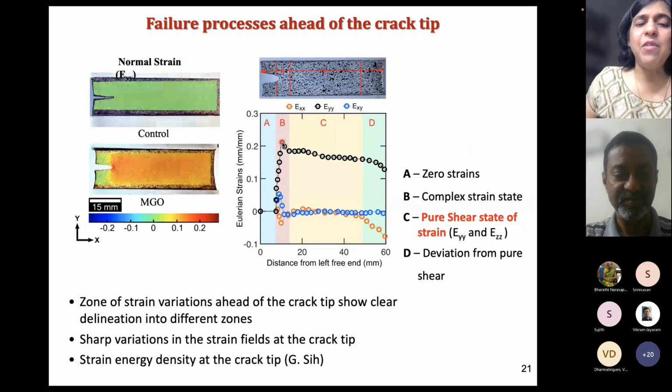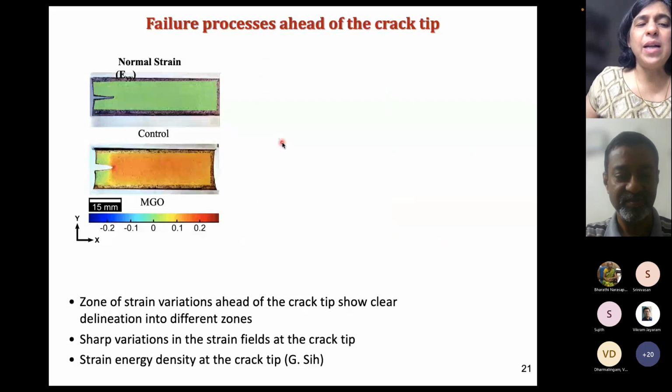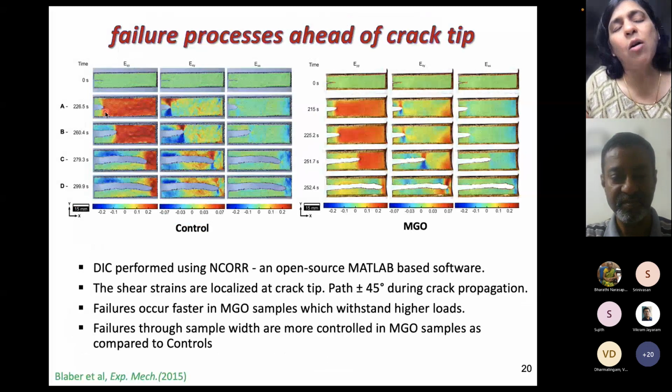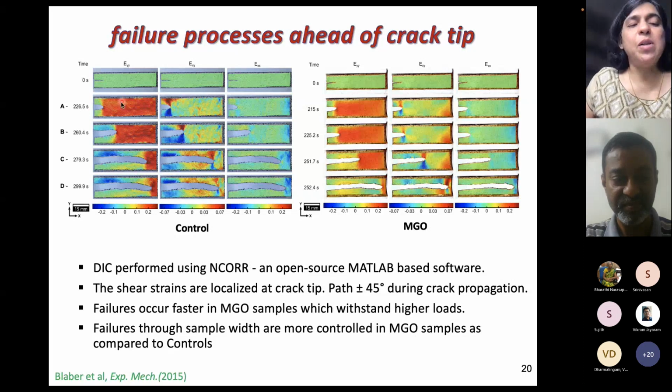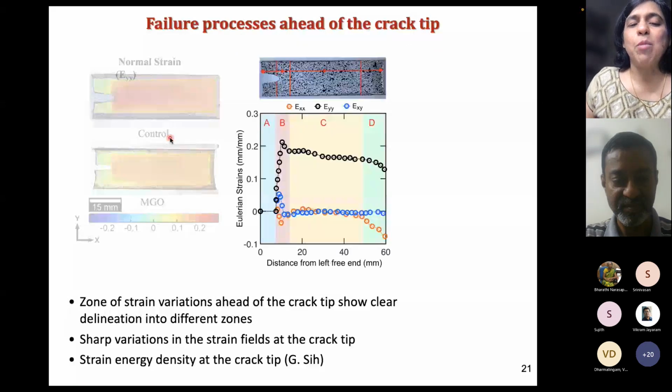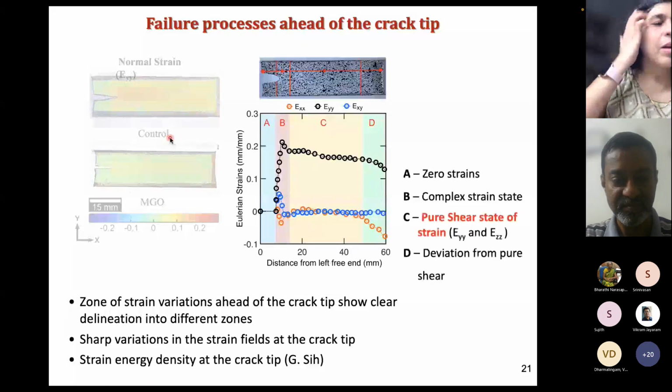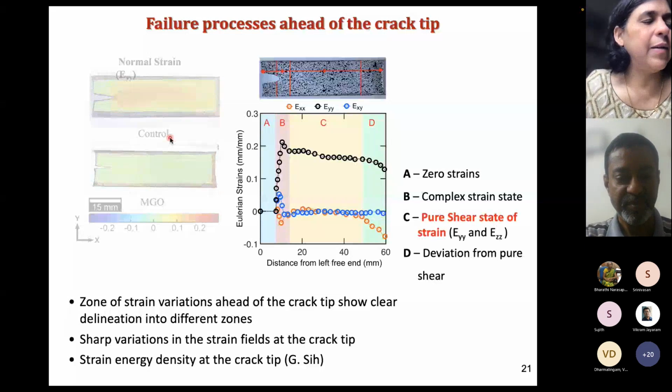Here specifically, I have used this first point when the crack grew. Immediately when the crack grew, so like I said, it stalls for a very long time at a certain length, and then it runs inside the sample. So just before the run is when we have calculated these parameters, which are plotted in slide 21. But that's a very good point.